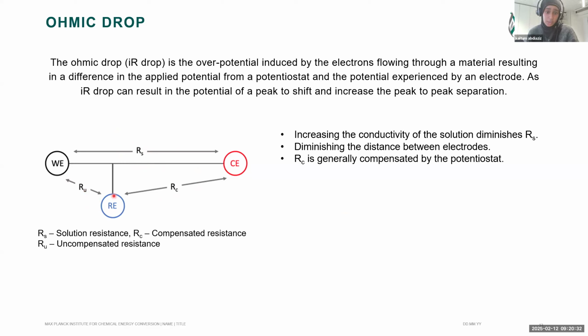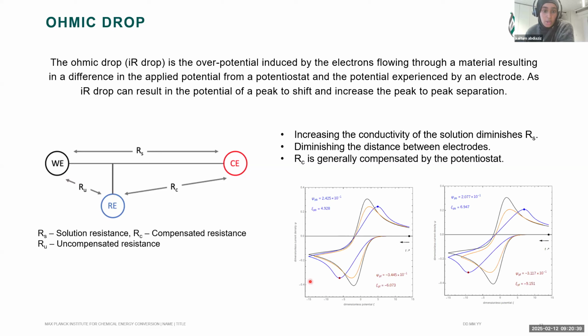And so some of these resistances can be compensated by the potentiostat, and here I show you an example. The black trace here is a system where there is no resistance, the blue is where you have some resistance, and the orange is the potentiostat compensated. And so you can see that it does compensate for a significant amount of the resistance. However, there is still some that is not compensated. So trying to minimize this is very important.